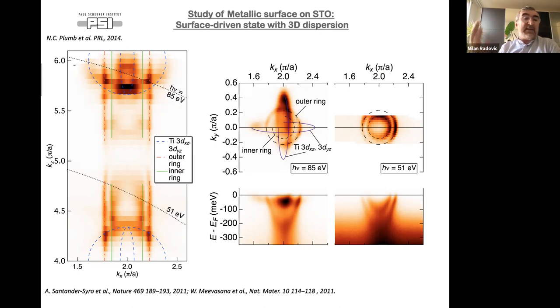For everything, how we do measurement, right? We do it with the circular plus, usually, just to not miss some kind of features there. And then when we understand the global band structure, we start to play with the polarization to understand the orbital character of the bands. And later, when we go to the spin measurement, then we exclusively do this with the linear polarization, vertical or horizontal. So it's very good if you know exactly the direction of alignment of your samples, right?